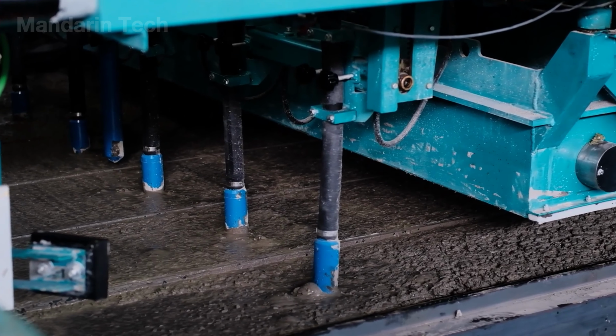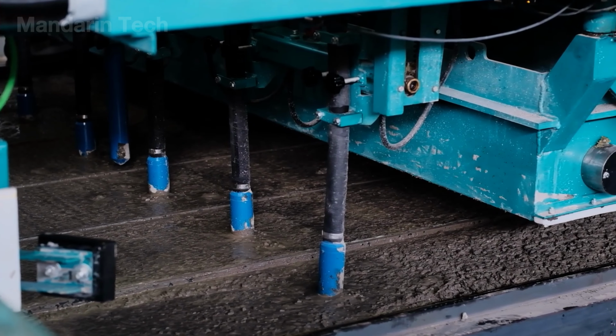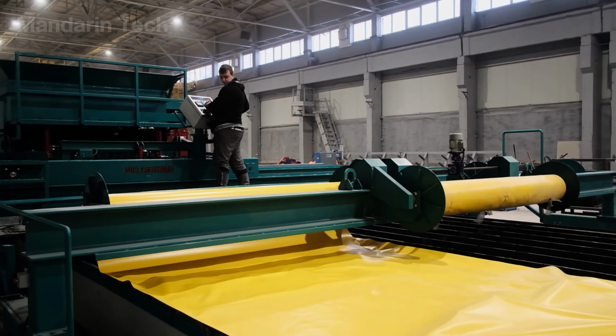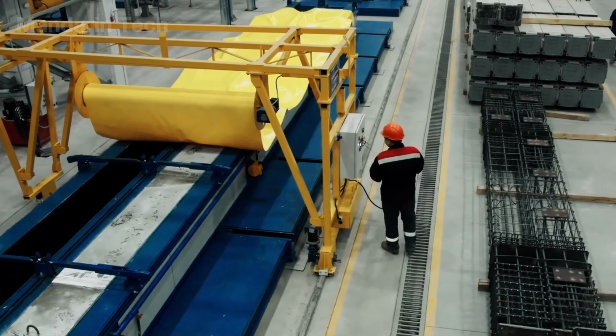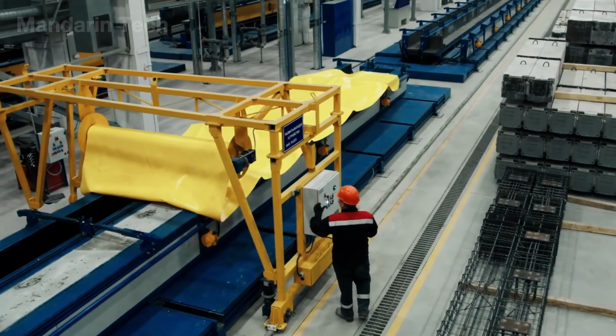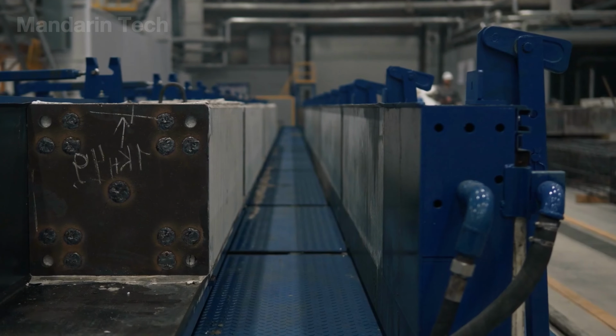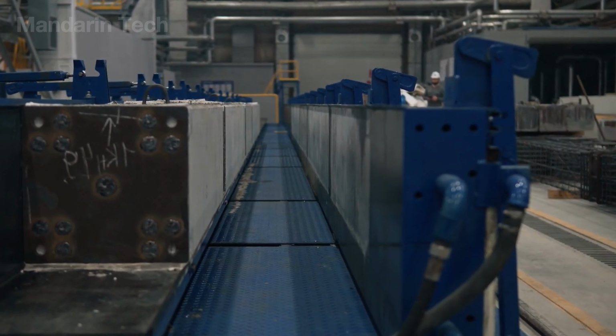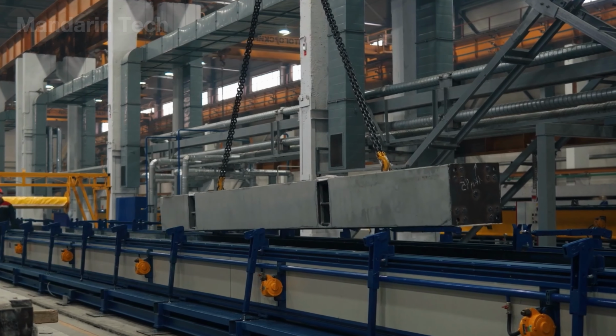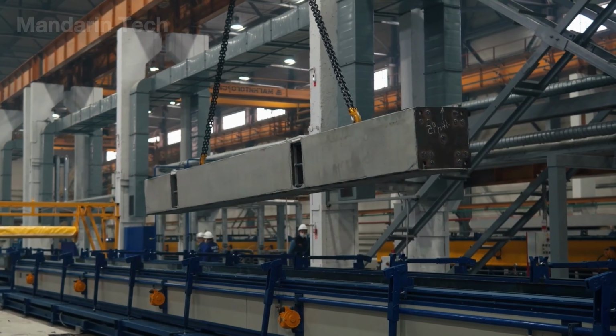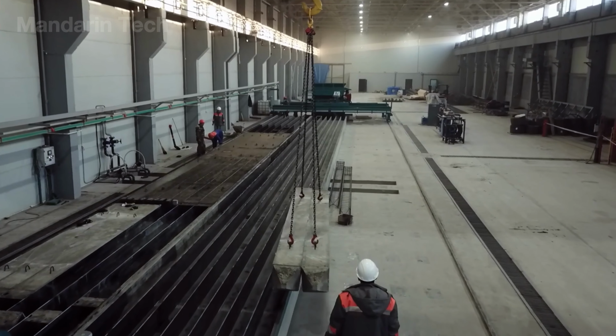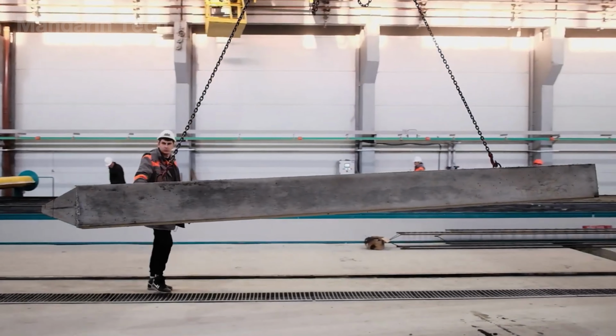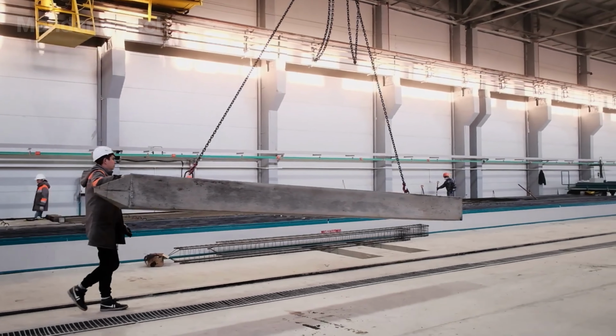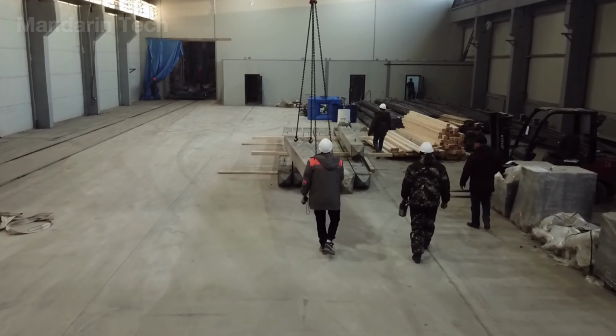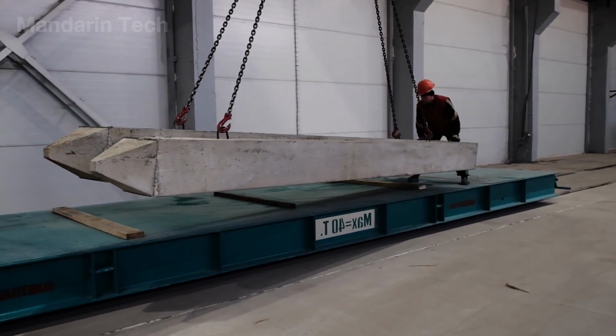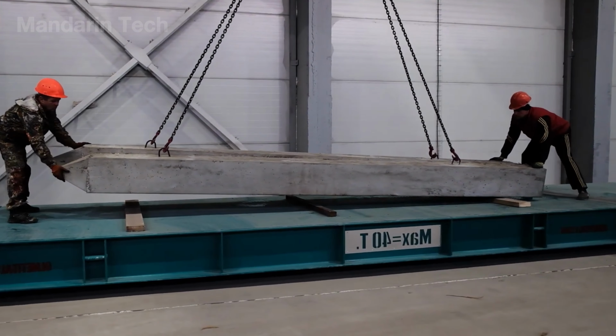Vibration systems operate simultaneously to eliminate air voids and ensure dense, uniform concrete that transfers loads evenly along the pile shaft. For pre-stressed piles, steel tendons are tensioned in advance according to design specifications, usually to about 70–75% of their design strength, allowing the pile to better resist both compression and bending during driving or pressing. The finished elements are then transferred to steam curing chambers at temperatures of approximately 60–80 degrees for 8 to 12 hours. When the molds are opened, piles measuring tens of meters in length emerge with sharp, clean surfaces and a flawless finish.